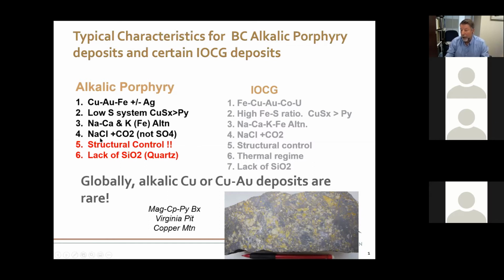So high chloride solutions and lots of CO2 are critical features. You get lots and lots of calcite. You get very little in the way of sulfates, which is important for ARD. And then finally, structural control on the mineralization is very significant, and those could be pre-existing structures and/or structures developed during mineralization. And then this key feature, which is the lack of quartz, which may have some implications in terms of the shape and size of these deposits, which will be points I'll make later.